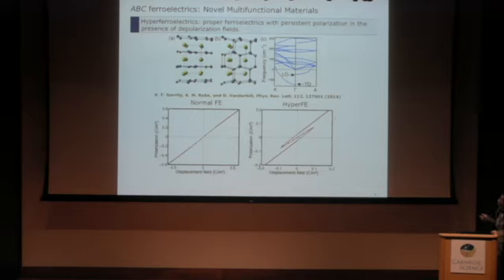So this is the phonon spectrum for the nonpolar phase. As you can see, both the TO mode and LO mode are unstable. This is very different from conventional proper ferroelectrics such as lead titanate, barium titanate. We know that only the TO mode is unstable in the nonpolar phase. The consequence of this unstable LO mode is that hyperferroelectrics can be polar even under ideal open circuit conditions.